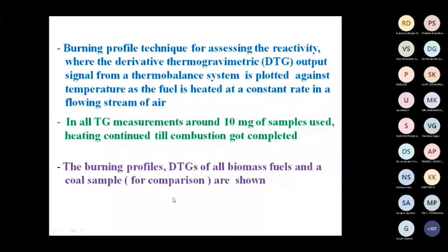So the burning profile is a technique for assessing, ultimately, the combustion reactivity of any fuel, whether coal or biomass, any solid fuel: the time, speed, and rate at which you are handling the combustion, heating. In the burning profile technique for assessing reactivity, the derivative thermogravimetric (DTG) output signal from a thermobalance system is plotted against the temperature. That is called the burning profile test. The fuel is heated in a flowing stream of air. In all TG experiments, around 10 milligrams of biomass sample is used. Heating continued till the combustion was completed. The burning profile or DTG of all biomass are also shown here.